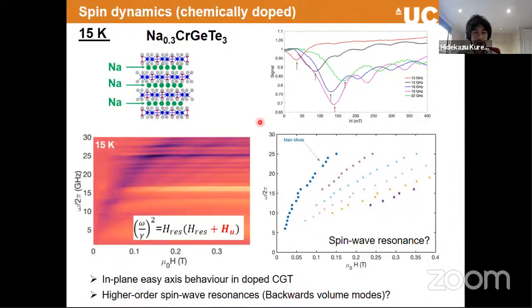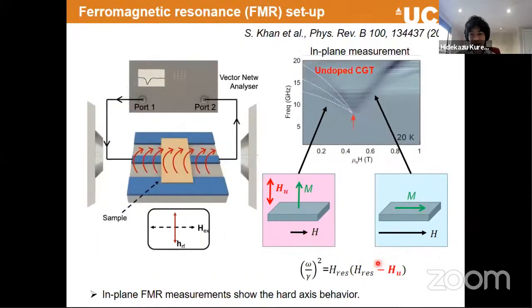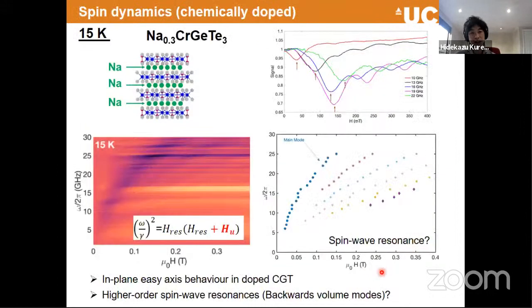So then I just want to show you the doped case. You can see that this peaky behavior simply disappears. We can see that this curve is just going down to zero energy when you sweep the magnetic field. That's the easy axis behavior. Now the sign inside of this bracket is positive, compared to the negative in the hard axis behavior. Again, this suggests the switching of the easy axis when doped.